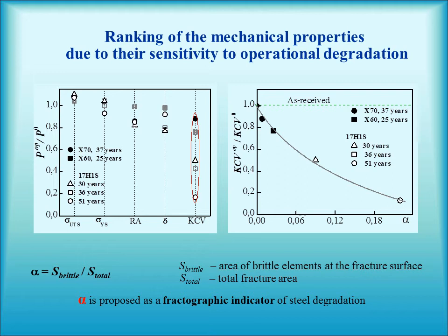It is important to note that cleavage was found only on the fracture surfaces of a heavily degraded steel, for which a drop of impact toughness was the most considerable. Occurrence of cleavage can indicate that a steel has reached a certain critical state and the following operation could be concerned with the real risk of brittle fracture. The substantiation of such critical state for pipeline steels would be a criterion for their further safe service.